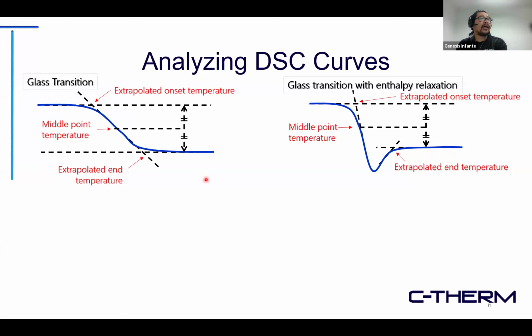So from all this curve, what we can get from this is what we call the onset temperature. And if we're trying to measure the temperature where an event starts occurring, usually we are referring to the onset temperature, not the middle point temperature, right? As right here. Another important temperature you can gather from here would be the extrapolated end temperature, the temperature where the event is now finished occurring.